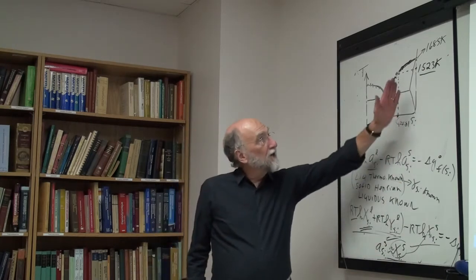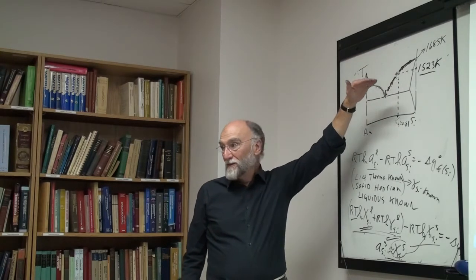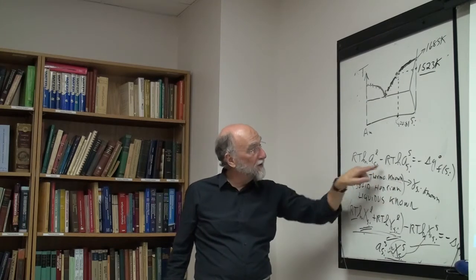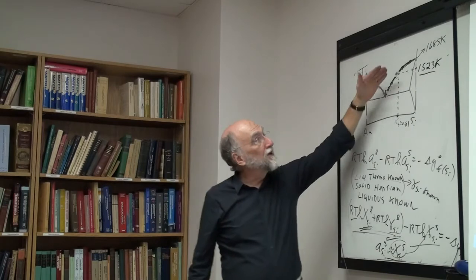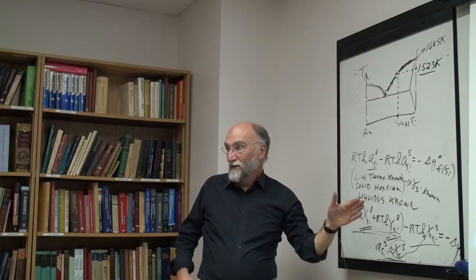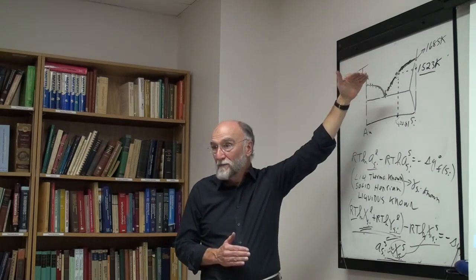Okay, so as the solid solubility increases, that also pushes the liquidus up. As this equation just becomes less than 1, this has to go the other way. If you have no solid solubility, that gives you the lowest possible liquidus. The more solid solubility you have, the more it pushes up the liquidus.